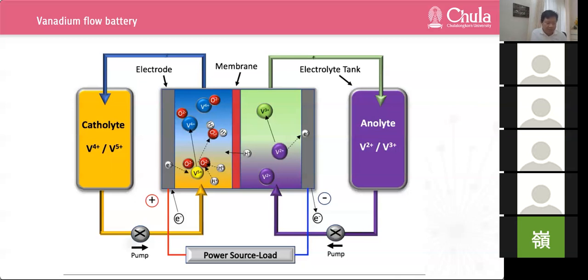And low solubility and precipitation of vanadium oxide, V2O5, over a wide temperature range. The low solubility of vanadium ions limits the system to a low energy density of 25 watt-hour per liter, because our active material is dissolved in the electrolyte. So solubility is a critical parameter in this case. And the potential for precipitation of V2O5 in the catholyte when electrolyte temperature exceeds 40 degrees Celsius for an extended period of time may reduce reliability and battery life.